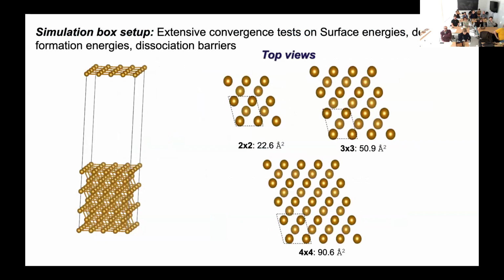So this is just to give you an idea of the slab thickness. Maybe you have seen in other papers smaller slabs, thinner thickness, and so on. But we have found that there are convergence problems if we use slabs that are thinner than this one. Okay, and this is just to give you an idea about the surface area of these slabs. So this is the first challenge when you want, of course, to account for defects.